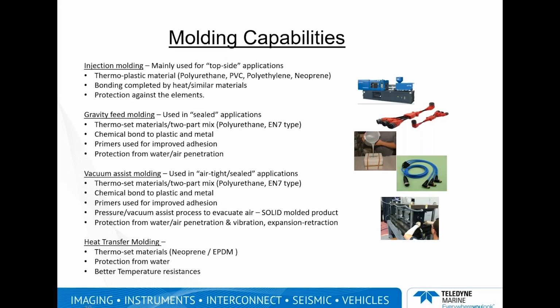The issue that you particularly run into is when the ejection seat has to fire off and the sequence is out of order because there's a wire that has been broken. If your ejection seat shoots off and your hatch does not breach, you have a devastating catastrophe. So it's extremely important when you have applications where the product cannot fail. We use these vacuum assist molding capabilities to be able to ensure really the integrity of the assembly and longevity of the assembly. The last capability is the heat transfer molding.